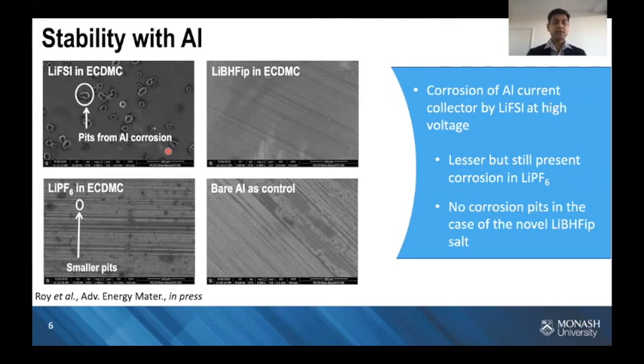Here, what we can see is after an electrochemical experiment at 5 volt, LiFSI leaves behind prominent corrosion pits on the aluminium current collector surface. Now, the pitting behavior is lesser in case of lithium PF6, but still present. However, in case of our borate, it's nearly non-existent, which means that not only is the borate salt stable and compatible with aluminium at high voltages, but it is also showing high electrochemical stability.